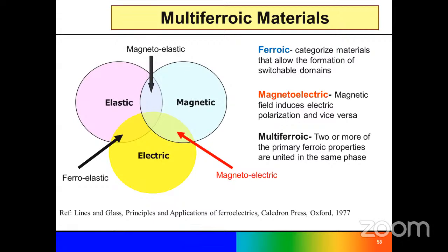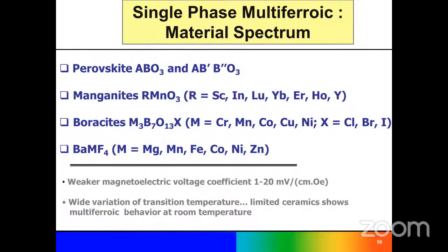Okay, so this perovskite material is very important for various types of applications. We also tried these perovskite materials in ferroelectric, magnetoelectric, and multiferroic forms. All these properties we can get from perovskite materials. Particularly for multiferroic memory devices, which show both magnetic and ferroelectric properties combined in a phase, we synthesized different types of perovskite materials. If you see in the literature, single perovskite materials have very low magnetoelectric coefficients, so they cannot be commercialized for applications.